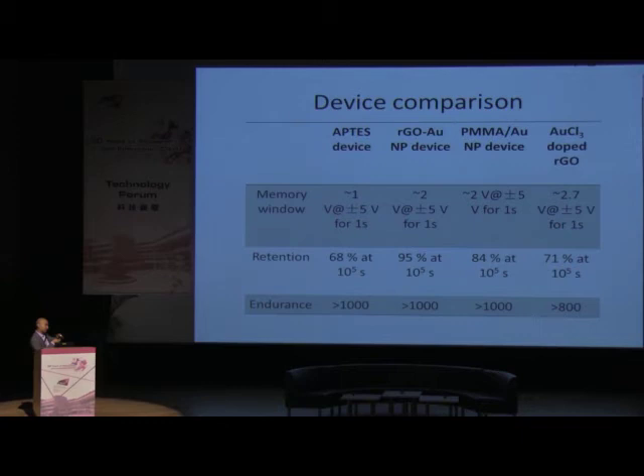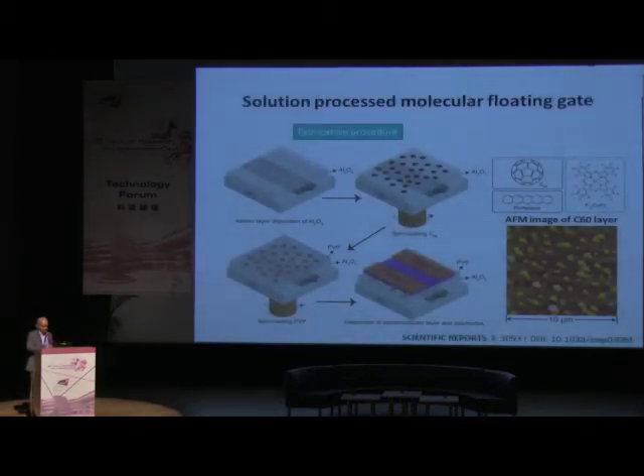Why? Because you have graphene on the top, you have a metal layer. This metal forms clusters. So at the end, it almost looks like a film where you have a lateral leakage. Because of that leakage, the retention time goes down a bit compared with the layer by layer device.